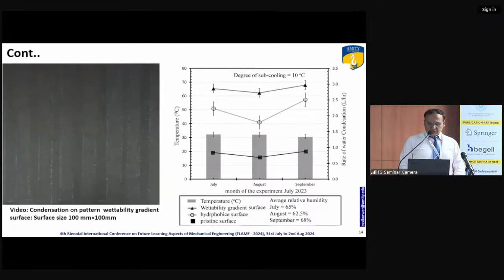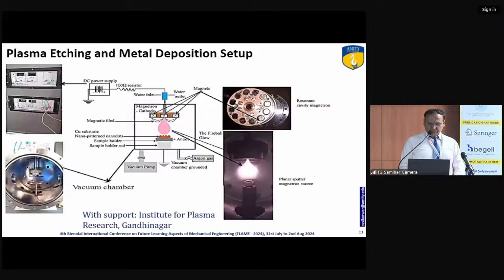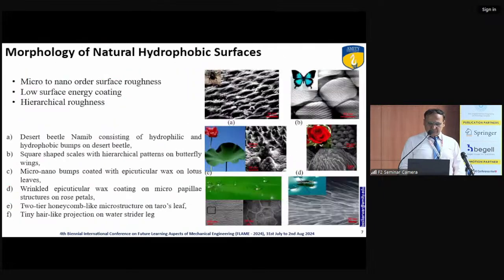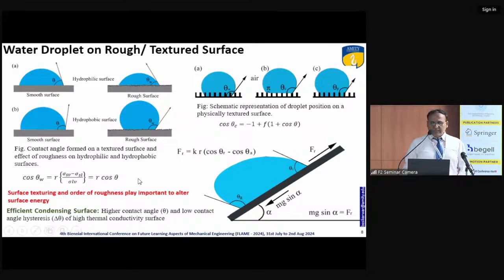So here you see a drop on a rough surface. Basically, if a smooth surface is hydrophilic and you produce roughness, it becomes more hydrophilic. If a smooth surface is hydrophobic and you produce roughness, it increases the hydrophobicity; it increases the contact angle. So you see the effect of roughness.